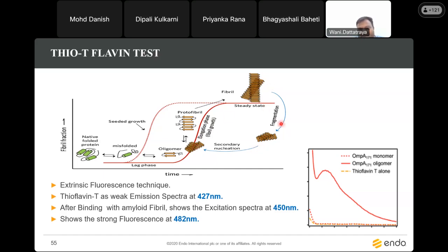So these fibrils are detected by using this thioflavin T test. This is one of the important tests we have to use to prove the aggregation state formation. If by using this technique you have proven that there is no aggregation, no fibril formation, then you can conclude that your product is okay. If there is a formation of fibrils, you have to work on the product development side.